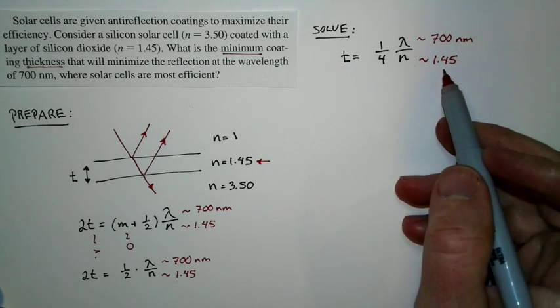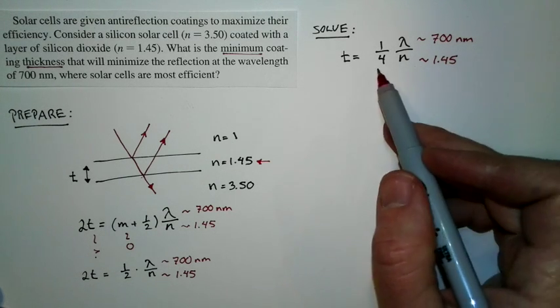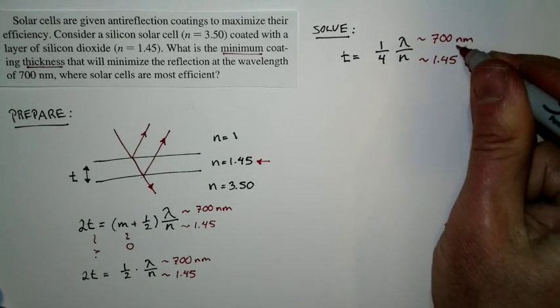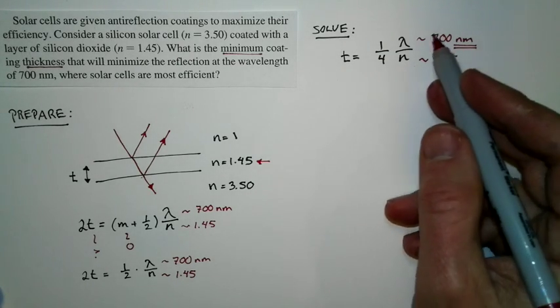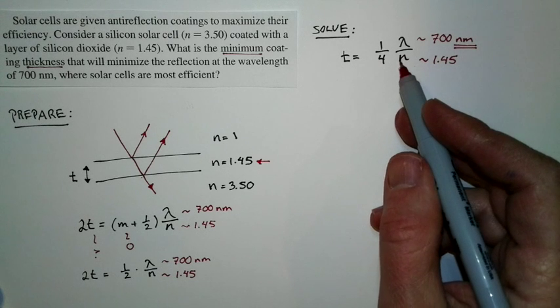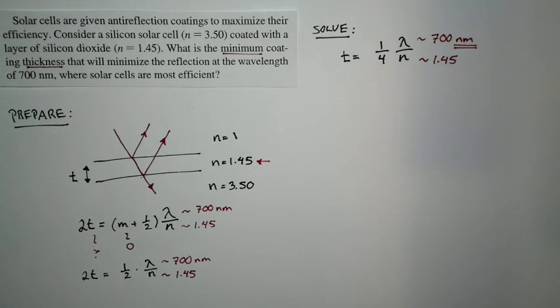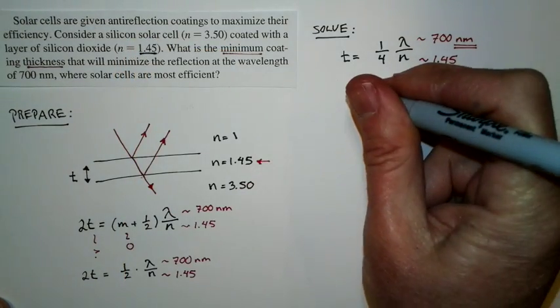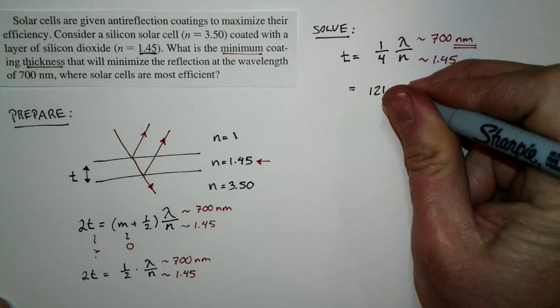Now notice this. I have 4 and I have 1.45. These are both just pure numbers. There's no dimensions with this. So I'm going to keep lambda in nanometers. Because whatever I put in here, whatever units I put in, these are just pure numbers. I'm going to divide numbers by numbers. The units won't change. And so I'll end up with nanometers at the end. This is a three significant figure problem. So I'm going to compute my answer to three significant figures. And if I do that for the thickness, I get 121 nanometers.